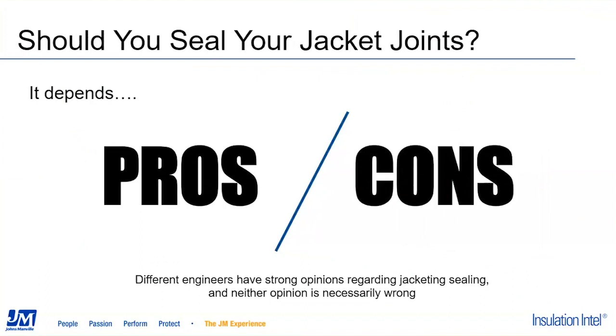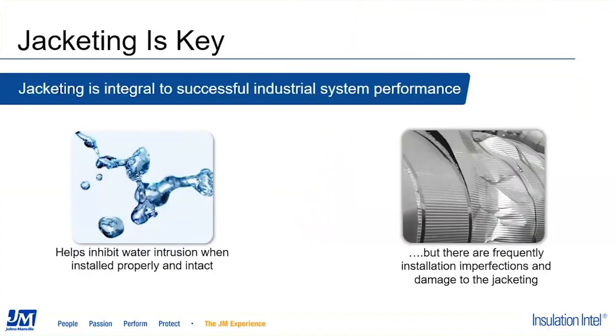If a sealant is used, it is critical to seal the inside of the joint and not the external lip. Most sealants are not UV stable and cannot be exposed to the sunlight. We have discussed that the proper material selection, system design, and installation of metal jacketing are important to the success of the system's performance of the insulation system. The main function is to inhibit water intrusion, and if there is no water that enters into the system, then there cannot be CUI.